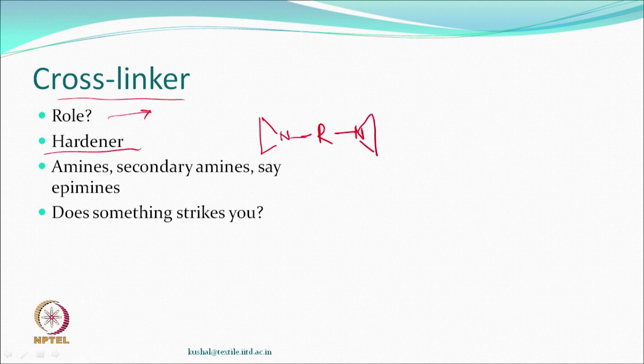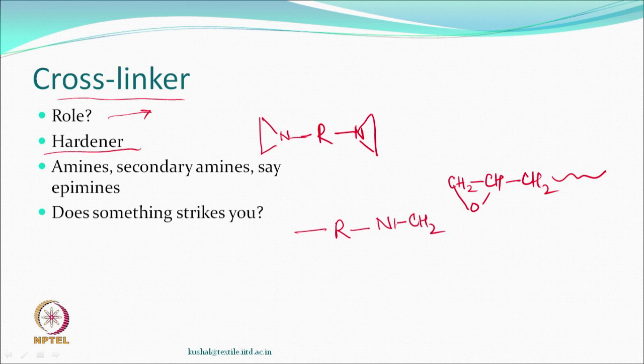So, these are cross-linking agents, as we know, they were used previously also. They can link with hydroxyl groups, they can link with other groups. Let us say in this case, if we have an epoxy group, which we just saw in our pre-polymer resin, this and this can react, the ring will open, and then what you will get is, let us say you have R, you have N, CH2, so this will become NH, and then CHOH and CH2 and so forth.